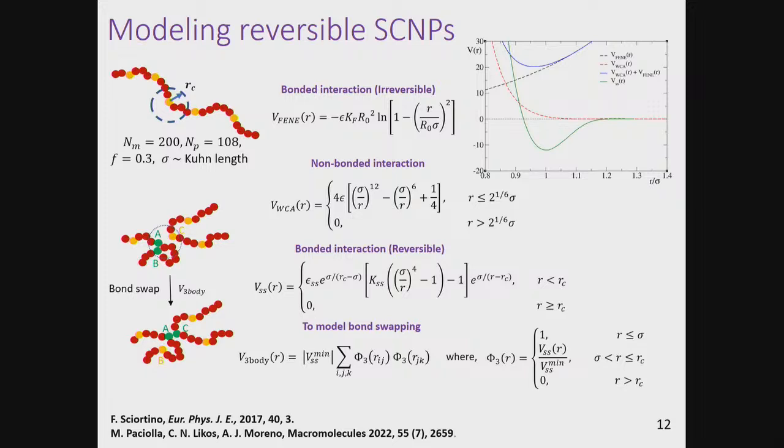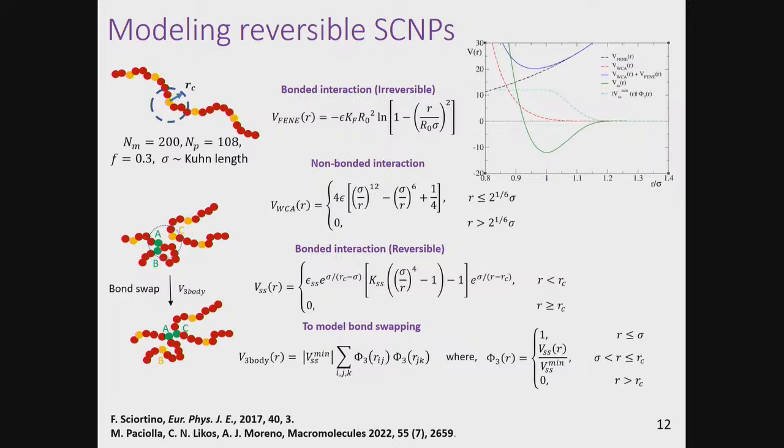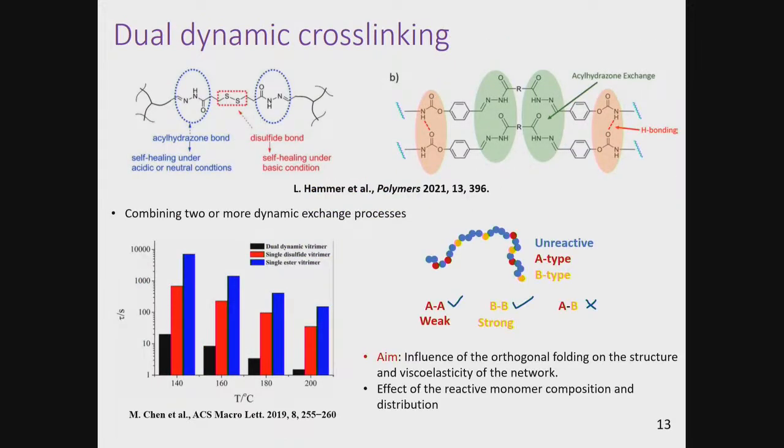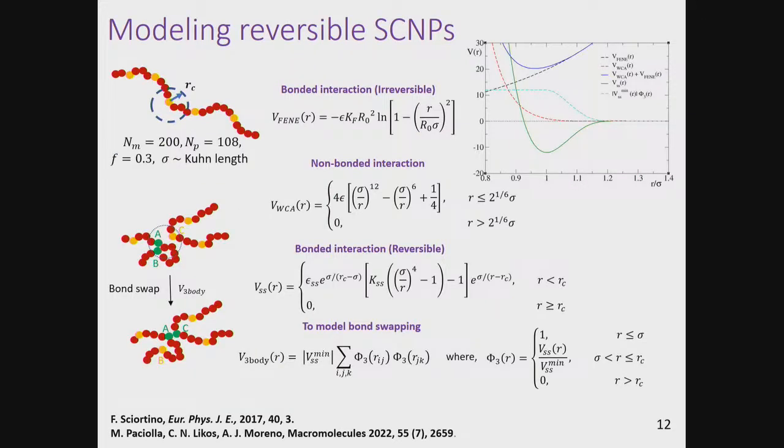And we chose it to be about 12 to 17 kBT in our model, which is much higher than the thermal energy. For the parameters that we have taken, we have about 0.9 as the bonding probability, so almost all bonds are formed in our system. I have not explained this fraction here, F. F is the fraction of reactive monomers. We have about 200 monomer beads in the chain, and about 60 of them are reactive. With such a fraction, we are able to achieve the highest possible bonding probabilities.